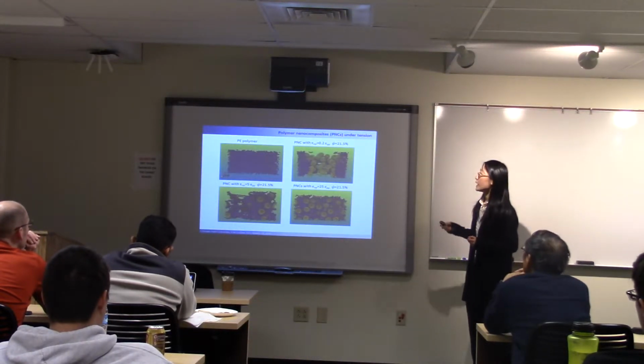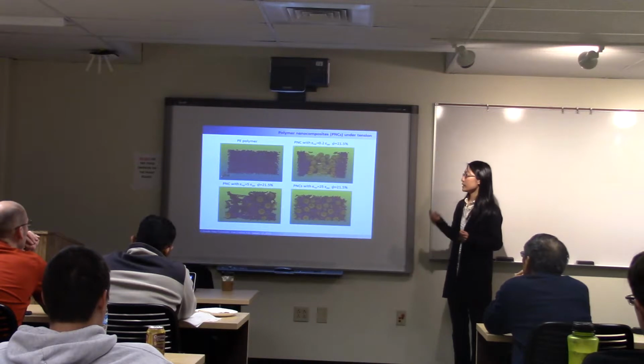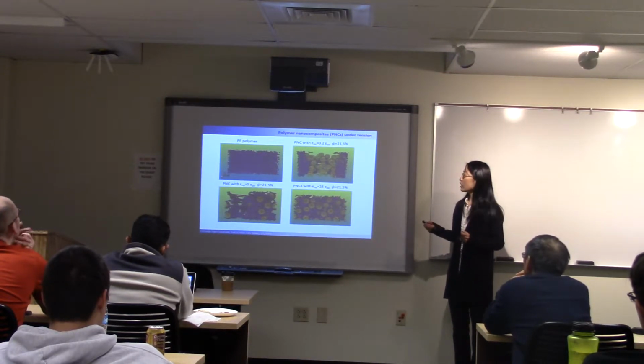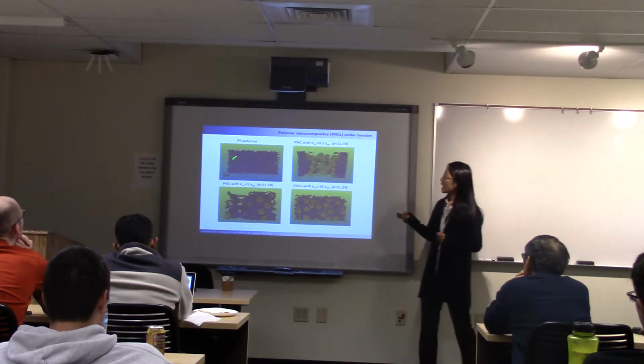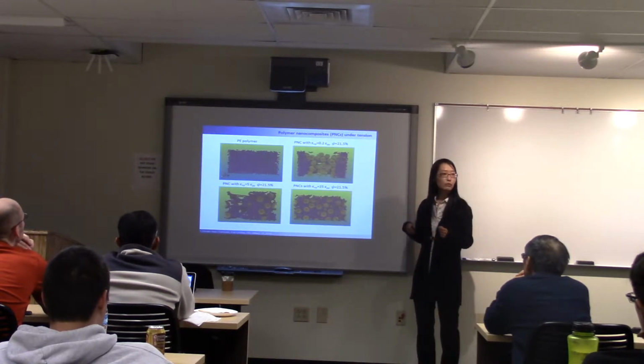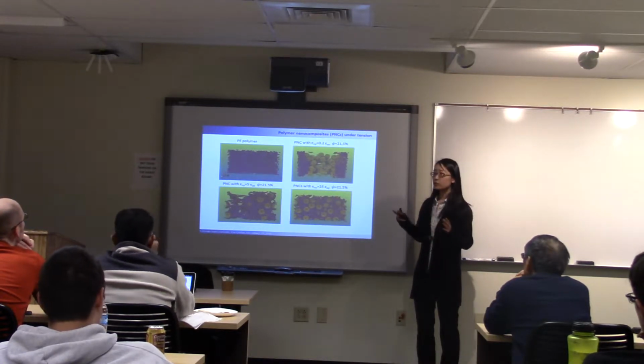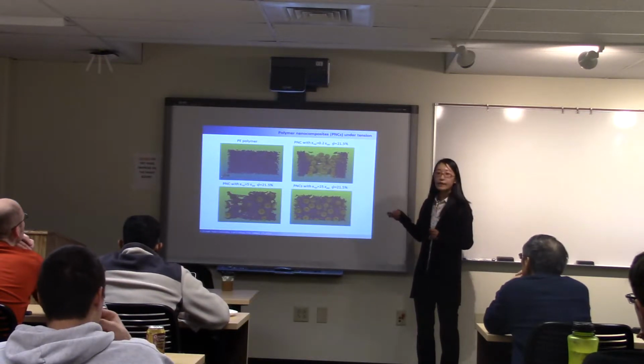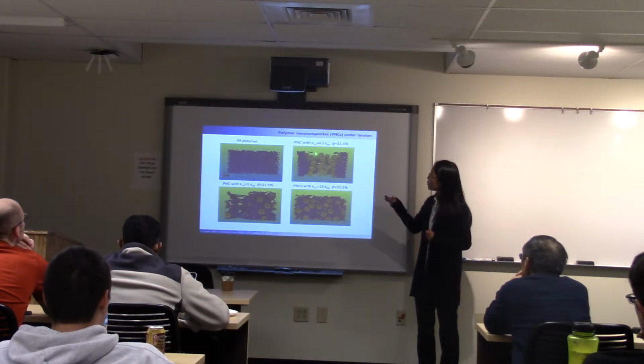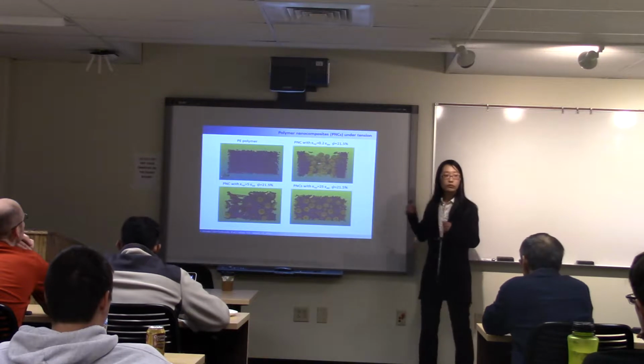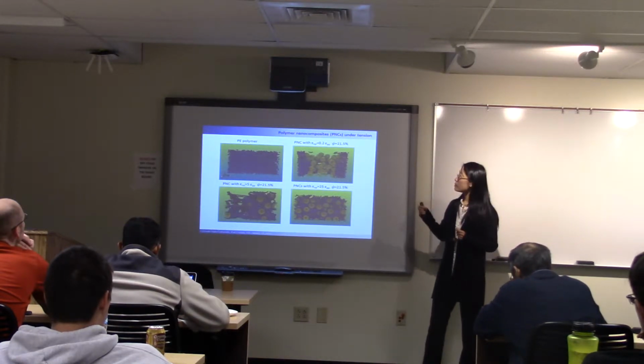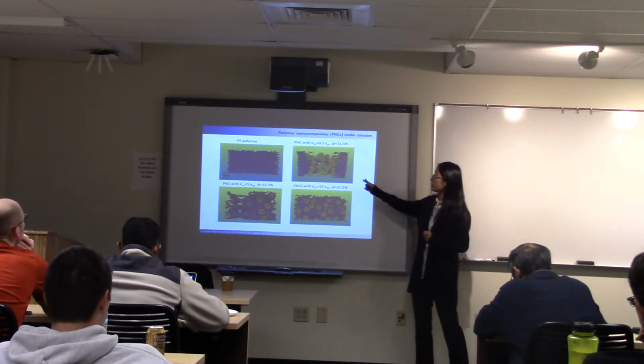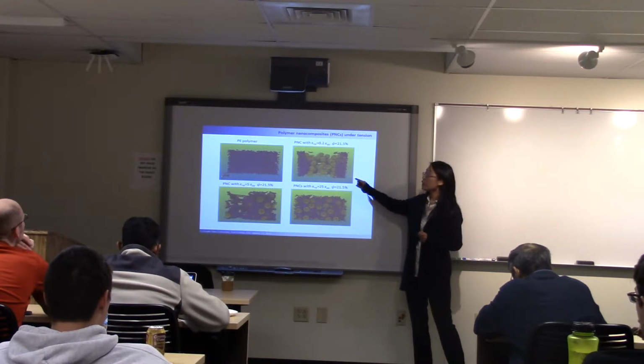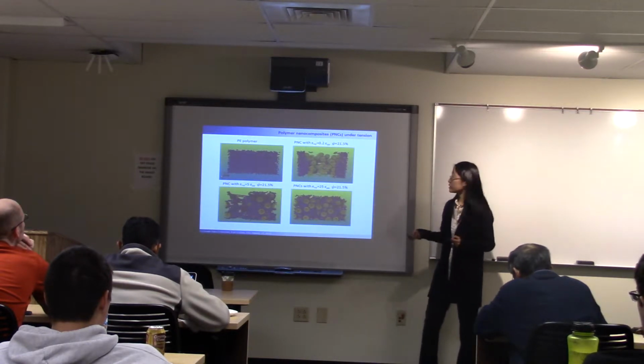First, let us look at some snapshots of the polymer nanocomposites under tension at a strain of 50%. The polymer with no nanoparticle addition has demonstrated uniform deformation at this strain level. And when we add the nanoparticle at low nanoparticle-polymer interaction strength, we can find there's nanoparticle agglomeration, which could potentially weaken the materials.